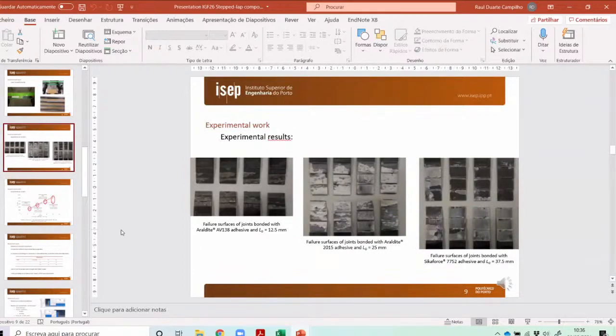So these are different bonding lengths that you had, from 12.5 to 37.5. In the 37.5, what we see is that you're having either adhesive failure or near-surface cohesive failure. But in the case with the 25 millimeter, it's perfect cohesive failure. What do you think is the reason that we are experiencing these two different failure modes? I'm actually seeing that also the adhesives are different.